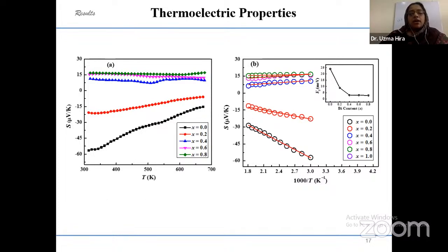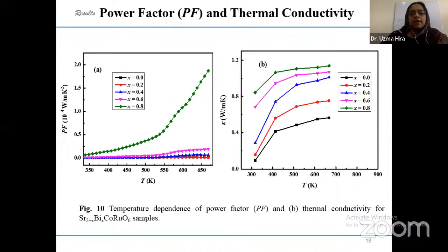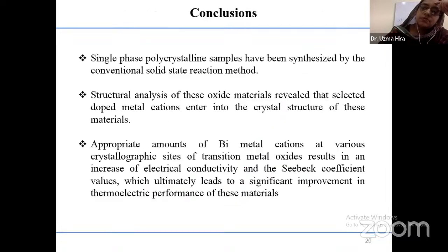So we have calculated the power factor using the Seebeck coefficient and electrical resistivity data, and you can see that with the highest dopant sample, 0.8, we have got a nice power factor value at high operating temperature. It means the dopant works well from a thermoelectric point of view in terms of power factor. Further, we have calculated the thermal properties by calculating the thermal conductivity as a function of temperature. You can see the thermal conductivity is increasing with increasing temperature.